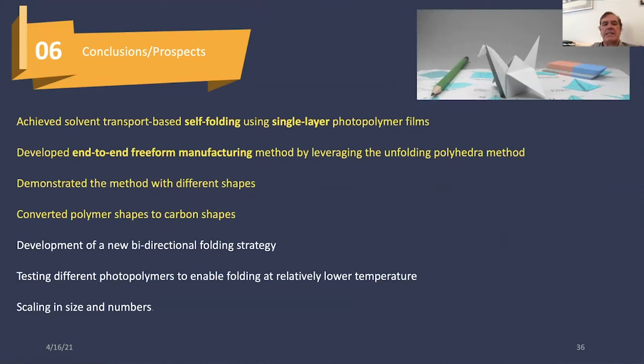So conclusions, we achieved solvent transport-based self-folding using single-layer photopolymer films. We developed an end-to-end freeform manufacturing method by leveraging the unfolding polyhedra method. We demonstrated the method with different shapes, converted polymer shapes to carbon, and developed a new bidirectional folding strategy. You can see this is in a different color. I didn't detail that yet, and so that is coming perhaps for the next talk.